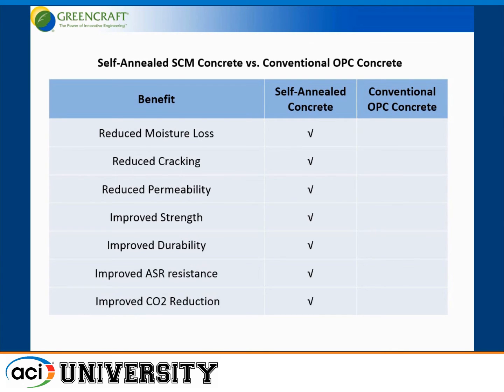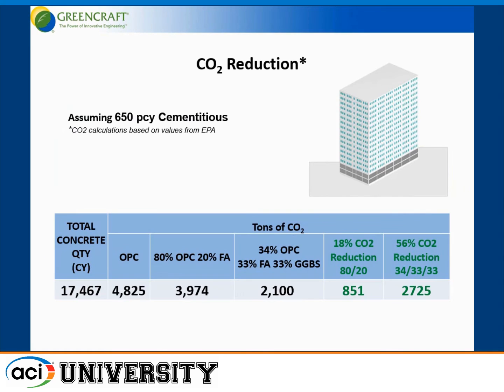So self-annealed concrete with high supplementary cementitious material replacement is a superior concrete compared to just standard Portland cement concrete. We have reduced moisture loss, reduced cracking, reduced permeability, improved strength, improved durability, and this comes up even more and more. Somebody said the other day, we're running out of good aggregate in this country, so ASR is going to be more and more of a problem, especially in the Midwest. We get improved ASR resistance with those mixes and improved CO2 reduction.